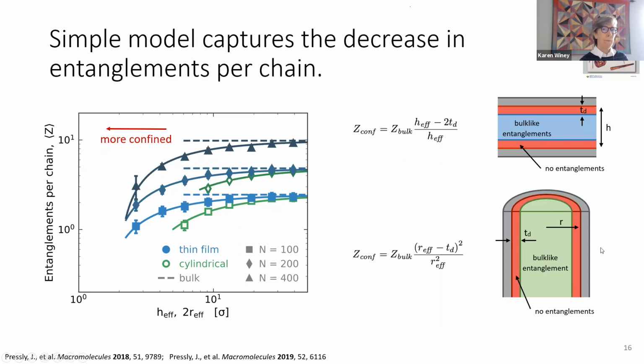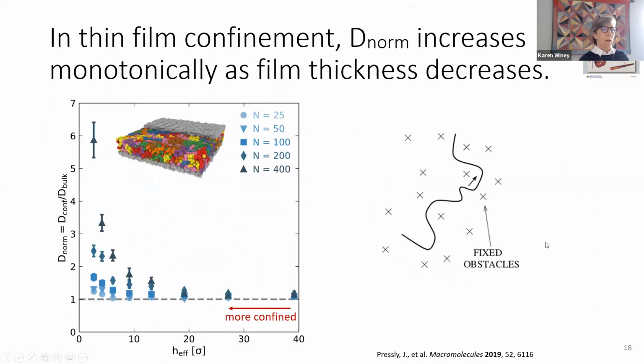Okay. So you can see I've erased some of the obstacles here. And if we have fewer entanglements, the diffusion should be faster. So as we get more confined, we can see this normalized diffusion coefficient increase. And it increases to a greater extent for higher molecular weights, because a higher molecular weight chain up against a wall is going to have fewer entanglements with other chains.